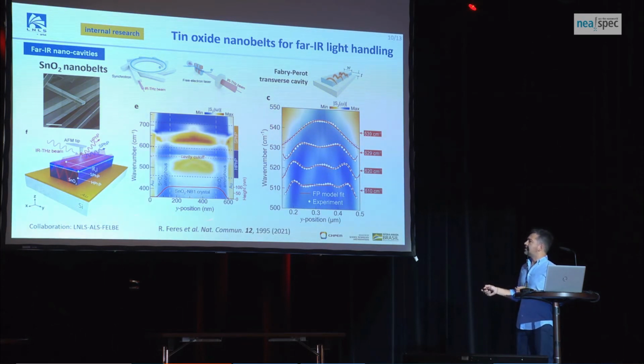As you can see here in this line scan, we just take several spectra transverse to one of those nanobelts. So you see here the profile of the nanobelt, and we can see a very different response for the two bands here. If we zoom in on this part here, we can see that we have some oscillations, some fringes that resemble a cavity. It means that this material is well organized enough to hold these oscillations, and with the Fabry-Perot cavity model, we could understand this as a real cavity. In this case, a transverse cavity.